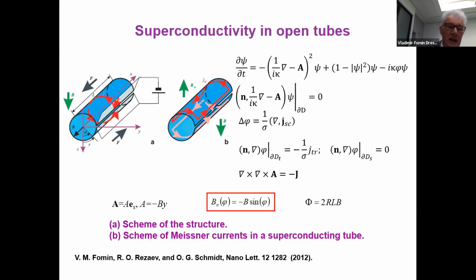The transport current flows orthogonally to the axis, and in the next slide, in the next panel, you see that in such a complicated geometry, two sets of screening superconducting current develop. One set in the upper part and another set in the lower part. As distinct from a planar structure, we have here two sets of disconnected superconducting screening currents, and this certainly will influence tremendously the properties of a superconductor in such a structure, as we will show in the next slides.